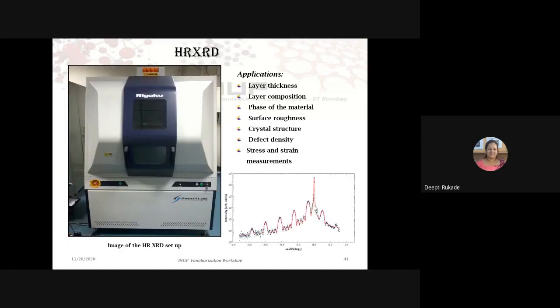Then we have HR-XRD. We can do all these kinds of measurements. Measurements in the sense we can do theta to theta, then we can do reflectivity measurements also. And things like layer thickness, layer composition, phase, or defects calculation can be done using those measurements. The system restriction is you cannot go ahead with powder samples. In that case, you have to drop cast your sample on a thin film in such a way that the powder does not come out. So the only limitation here is we cannot do HR-XRD of powder samples.